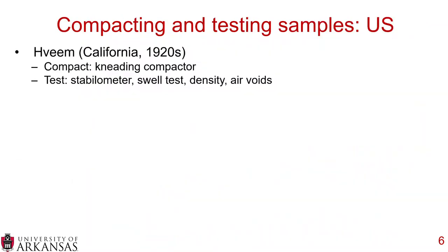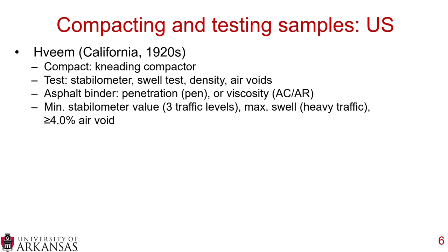So if you look at the United States, I recognize this is a United States-centric presentation, but that's because I'm in the United States. So if you look at the United States, Hveem in the 1920s out of California, they used a kneading compactor as the compaction mechanism. And then for tests, they used the stabilometer, the swell test, density, and air voids. The asphalt binder uses either the penetration grade or the viscosity grade, which can be either AC or AR, depending on if you age it. And you have a minimum stabilometer value, it's based on your traffic level, a maximum swell value just for heavy traffic, and you're targeting greater than 4% air voids.